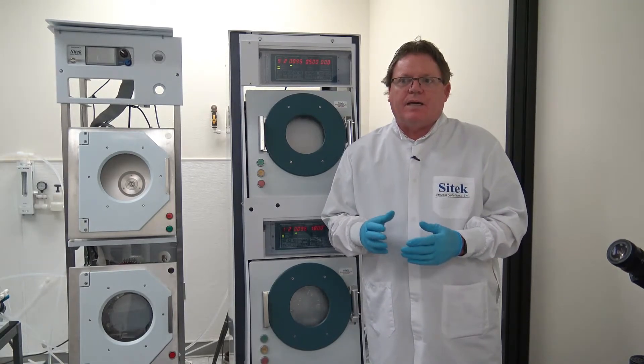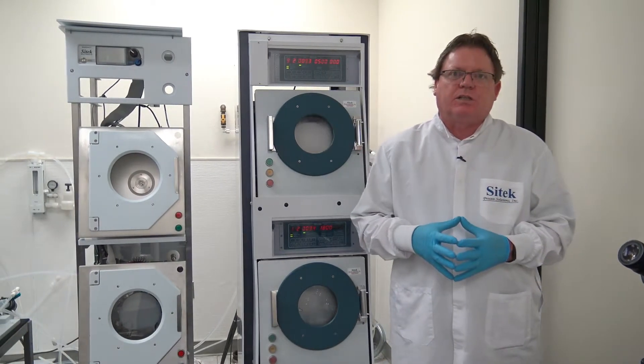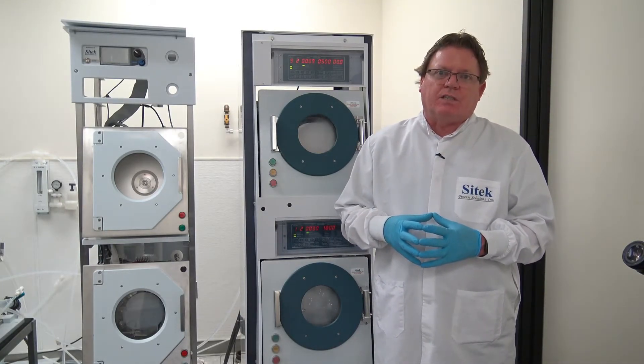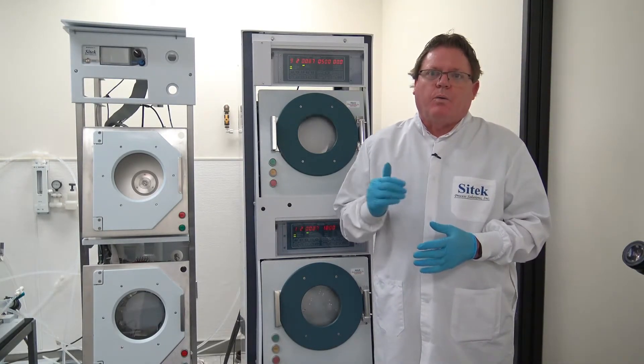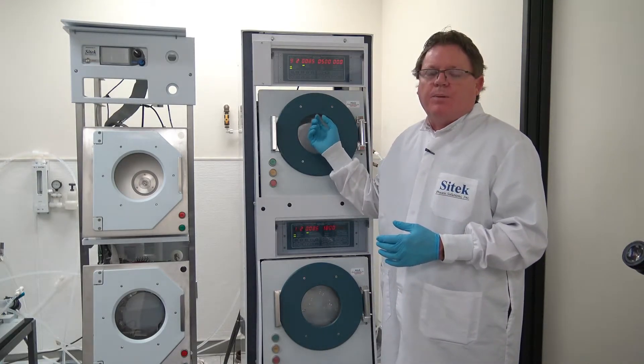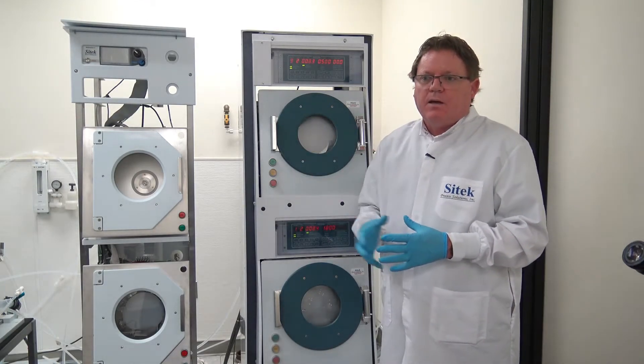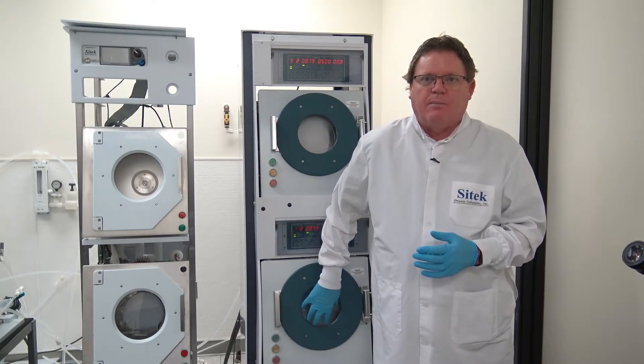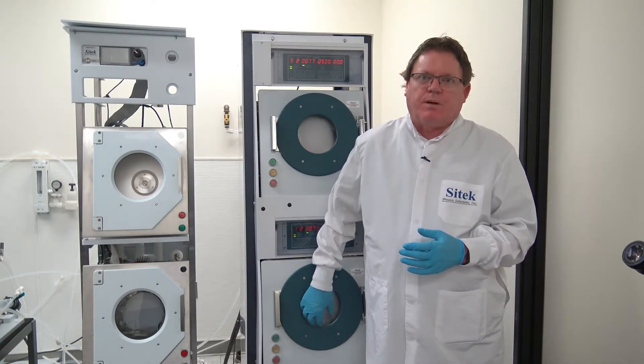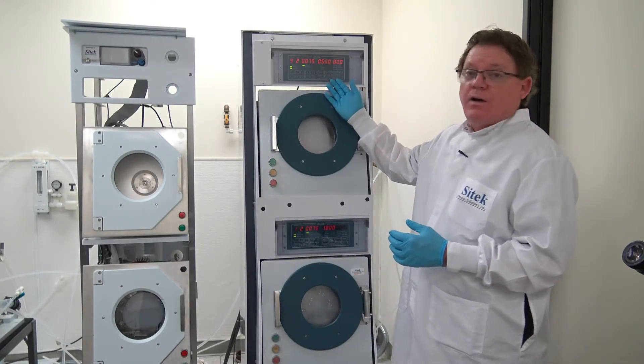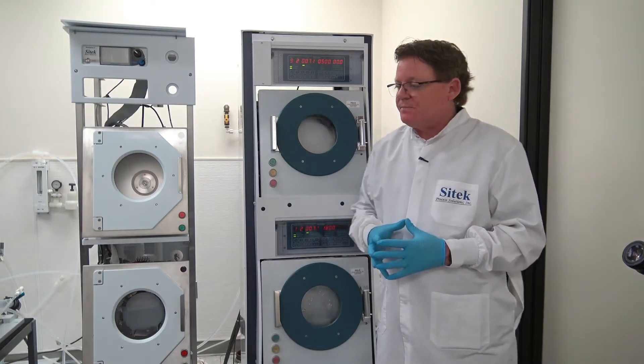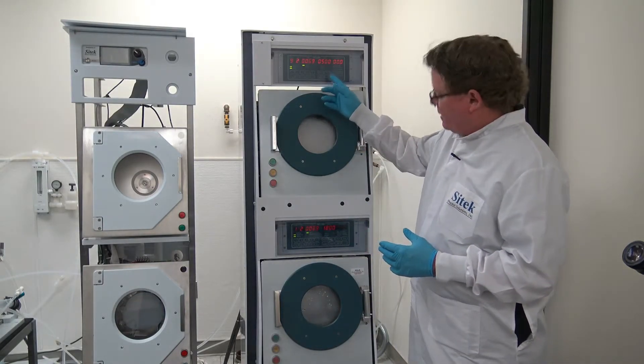The reason I say it's important is at semi-tool at least, when I worked there in our process lab in Montana, there's lots of tests done for particle control. We always found the lower RPM gets better particles. So I'm saying this to the customer, if they're used to having Verteq and they're used to running high RPM, they might want to look at dropping the RPM down to anywhere between 500 and 800. And they should get better particle counts, if they're doing particle testing. So we have about a minute to go, a minute and a half.